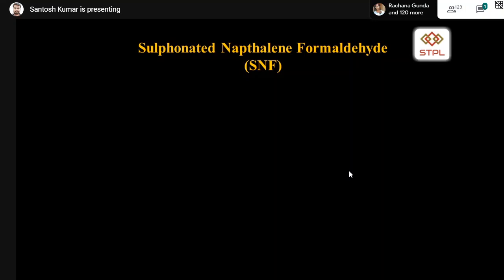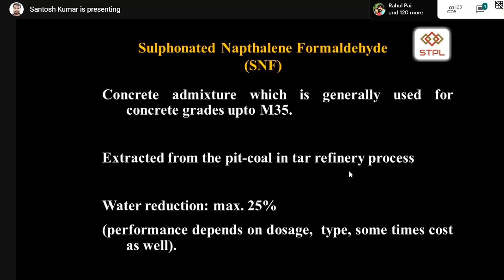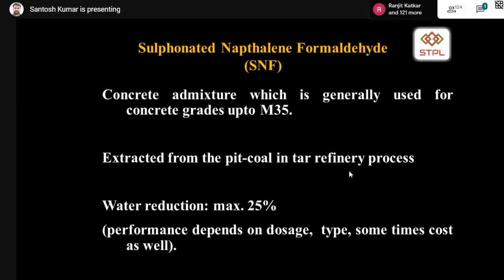And coming to the major types of admixture, there are many types of chemical admixtures in the market, but frequently and regularly used there are only two types. One is sulfonated naphthalene formaldehyde based, which can be used up to a grade of M35. And these sulfonated naphthalene formaldehyde are extracted from the pit coal in the tar refinery process, and the water reduction may be up to a maximum of 25%.